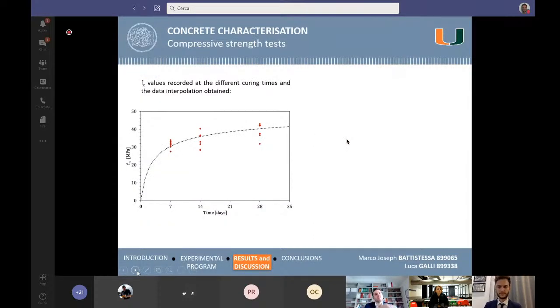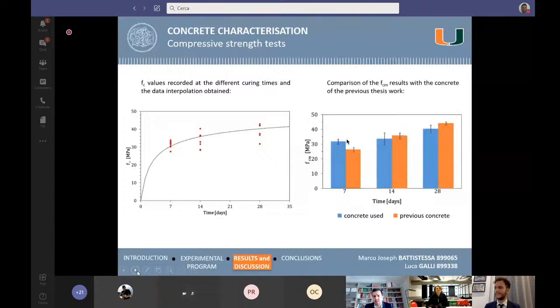Well, now let's have a look at what we got in terms of results. Here we can observe the results obtained by the compressive strength test performed at 7, 14 and 28 days of curing. And also we can see the estimated evolution fitted according to Eurocode 2. While on this graph we can see the mean compressive strength of each curing period highlighted and compared to the one obtained in the previous thesis work.